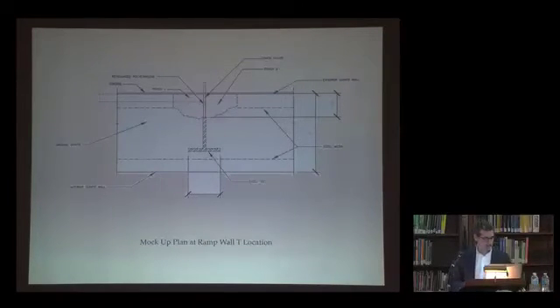The section of this is the gunite wall in section. This is the T. We've removed in this section the damaged gunite. We have treated the T with rust inhibitors and coatings. Then we've applied our patch, and I'll show you this in a second. And then, depending on the amount of movement, we filled this from the T forward with a specific material, and then depending on the amount of movement, we filled the end with another material, which all got coated with an elastomeric coating. And all of them have to work in unison. We can't have any separation. If we do, we'll end up with the same results as we saw coming out of the accelerated weathering.